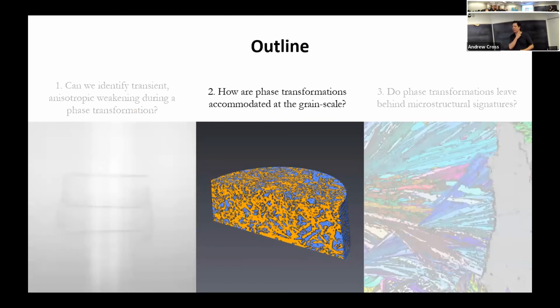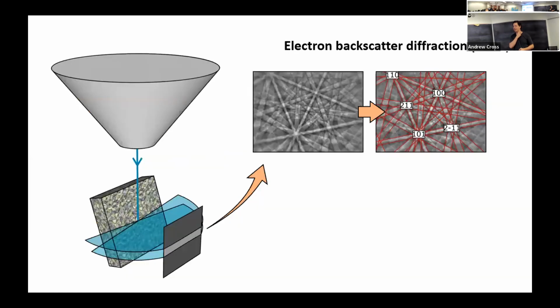All right, so let's look at what this actually looks like on a microscopic scale. And again, from here on, this is mostly what Rheoli's been working on for her postdoc project. A technique that we'll lean on quite heavily here is electron backscatter diffraction. So we've got a highly polished tilted sample in a scanning electron microscope. We're going to fire an electron beam at the sample. Those electrons are going to interact with quite a small activation volume near the surface of the sample, and they're going to diffract off in all sorts of directions. They're going to diffract along crystal lattice planes to produce a series of cones like this.